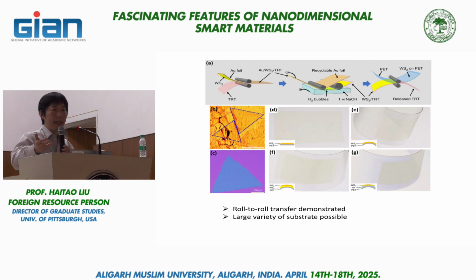A particular challenge here is that a lot of the metal substrates are conductive. So if you want to make an electronic device, you have to move it to another substrate that is insulating. And usually this is either a plastic substrate if you're interested in doing flexible electronics, or something like a silicon wafer where you can do large scale lithography, because in that case you need a flat substrate to work with. So there are a lot of tricks being developed to exfoliate the single layer on the metal substrate.